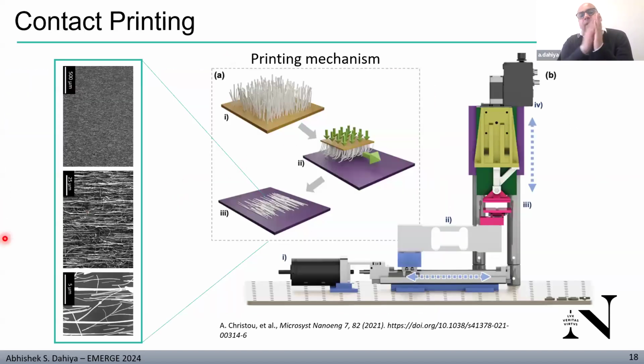And the other technique we are developing is a contact printing setup. Contact printing is normally used for printing of vertically aligned nanostructures, unlike the direct roll printing, which prints laterally aligned structures. This printing technique is based on shear forces between the donor and receiver. So here you can see in the printing mechanism, we have a donor, we bring it in conformal contact with the receiver, and once the forces are applied to have this conformal contact, we have a sliding force in this direction, and the wires are printed laterally onto the receiver substrates.